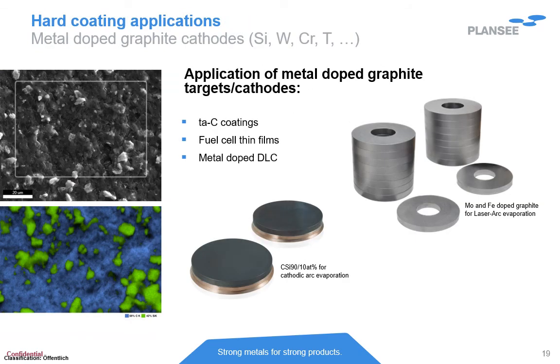Related to the very high temperatures applied in hot pressing technology, we would like to introduce new products described by the name metal-doped graphite. Some examples of arc evaporation cathodes, as well as targets for laser arc evaporation technology, are shown in the pictures. As we use a very small size of metal particles, we can achieve a very homogeneous distribution of these particles in the graphite matrix, shown on the left side. What are the applications? From today's point of view, these are high hardness TAC coatings, metal doped DLC with still very low friction coefficient but increased thermal stability, and also thin films for fuel cell interconnector coatings.